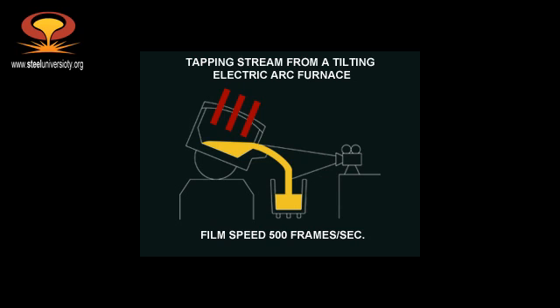This first sequence shows the furnace stream entering the ladle. As is evident from the short movie, the stream is not a compact stream — it actually tears apart, is full of holes, and is entraining copious quantities of air into the ladle. This affects steel quality by re-oxidising the steel and the alloying elements present in the steel.